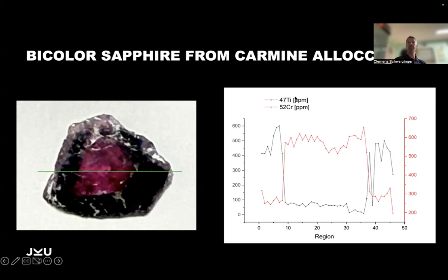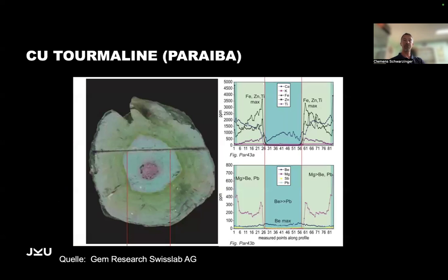Iron very often is at the same concentration. It just takes a couple of ppm, like in this case 400 ppm of titanium, to give us this intervalent charge transfer complex. I know lots of complicated words here, but just for the information, you need titanium and you need chromium to make these bicolor sapphires. And they grow from the center towards the rim just by having different solutions where they grow in, with different chemical compositions.